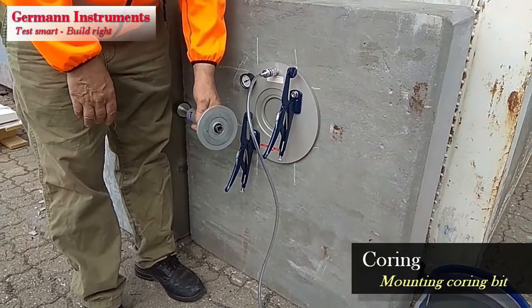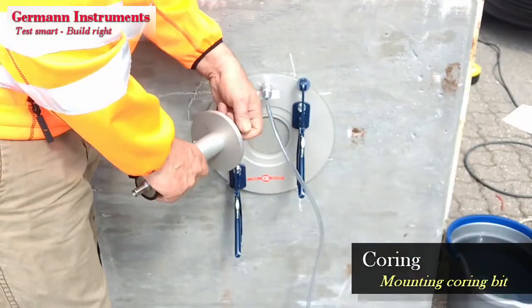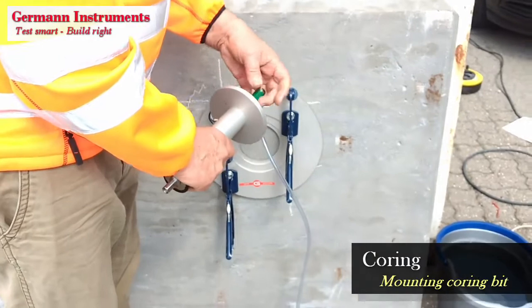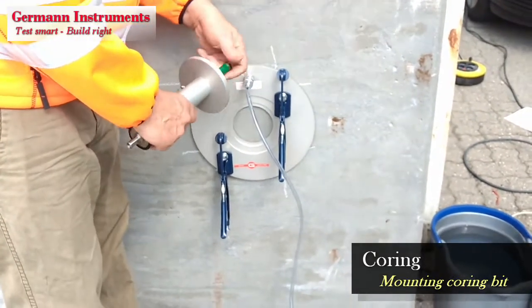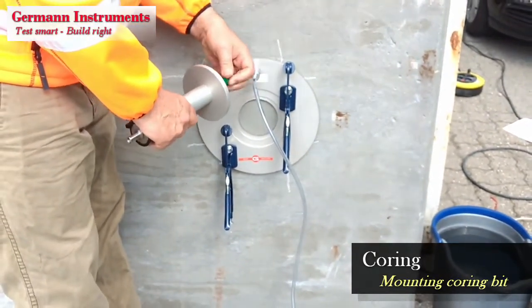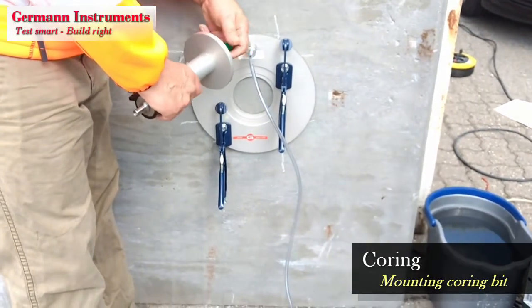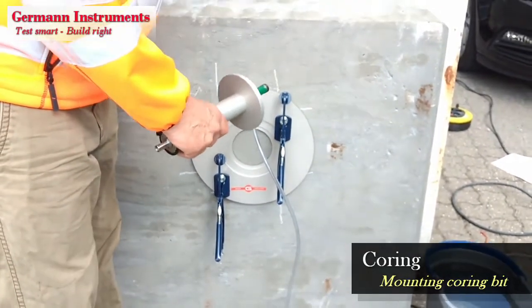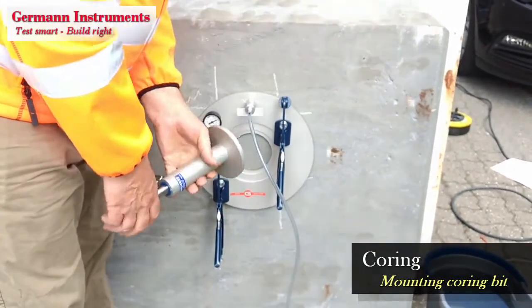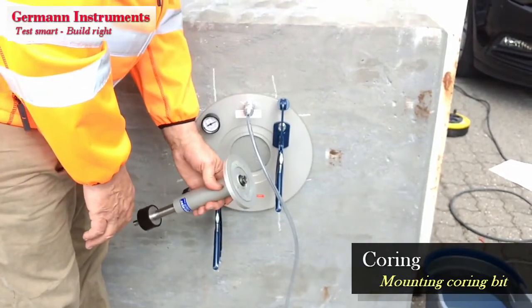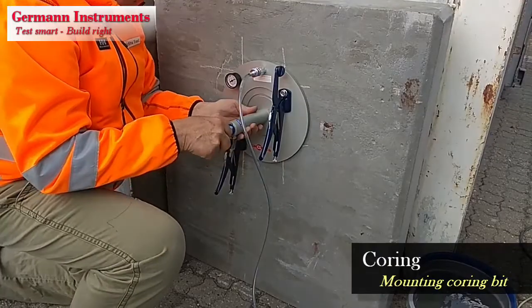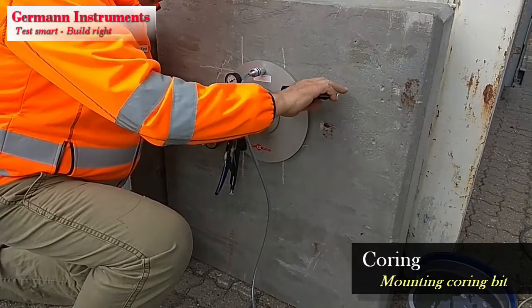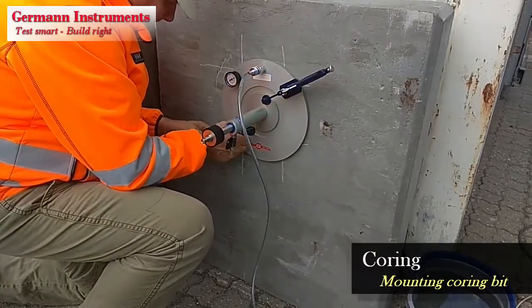A 19 mm key positioned on the recesses at the top of the shaft and a 17 mm key at the coring bit's barrel. The green coring bit could be too long depending on the height of the suction plate after initial suction. Start out with the red coring bit, and terminate the cord hole with the green bit. The drill unit is positioned in the vacuum plate and kept firmly attached by the adjustable clamping pliers.